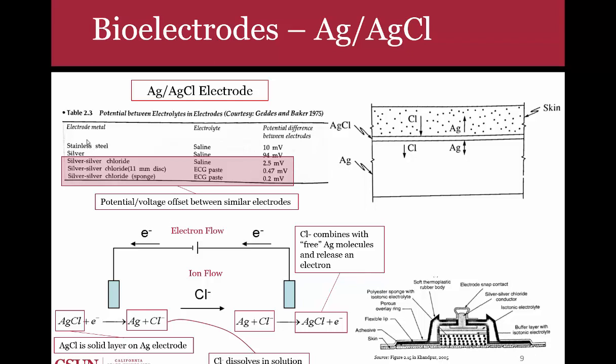residual voltage. And so it turns out that we've studied different electrodes and have found that these specific electrode types in this table here, when you use the same electrodes in the same solution, will produce a very small voltage difference, but we're on the order of now millivolts instead of volts. So you can use stainless steel electrodes, and in fact these are mainly used for measuring EMGs invasively. And you see that if you put two stainless steel electrodes in saline, which is basically an electrolyte, you'll get a 10 millivolt difference between those two stainless steel electrodes, which is very small compared to what you were getting earlier. If you put two silver electrodes, you won't get 0, you will get 94 millivolts.